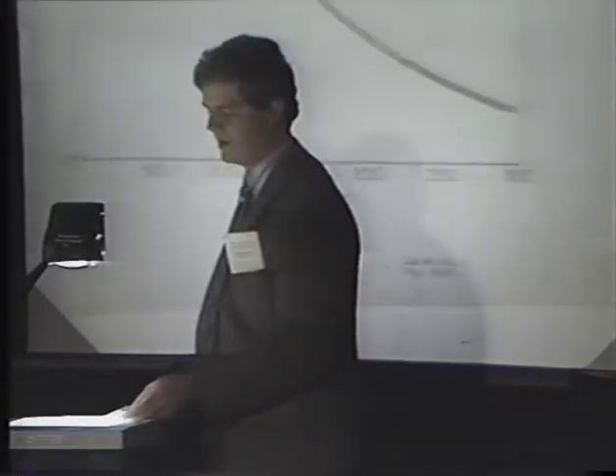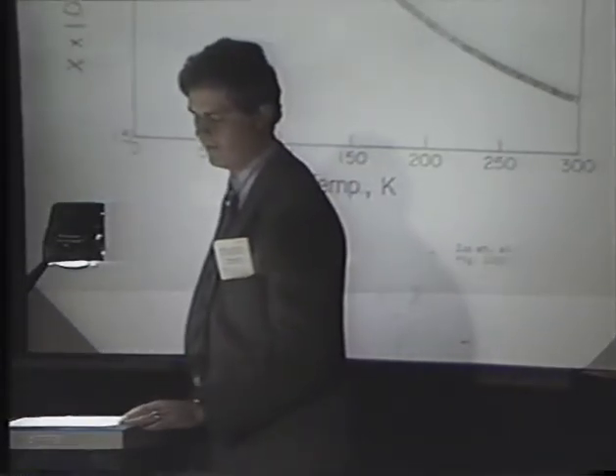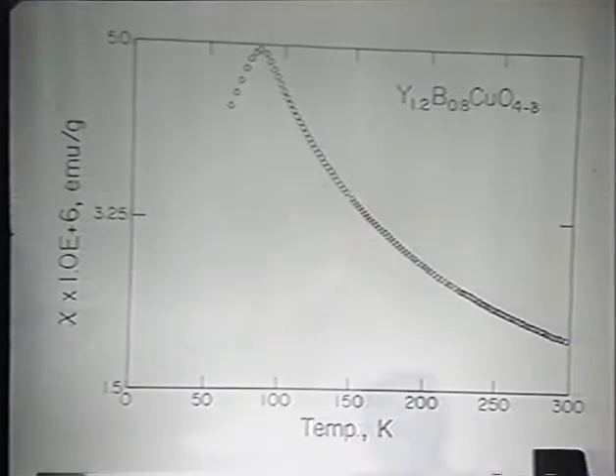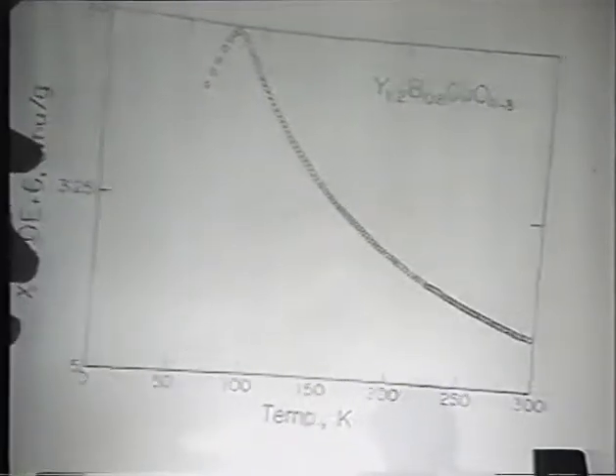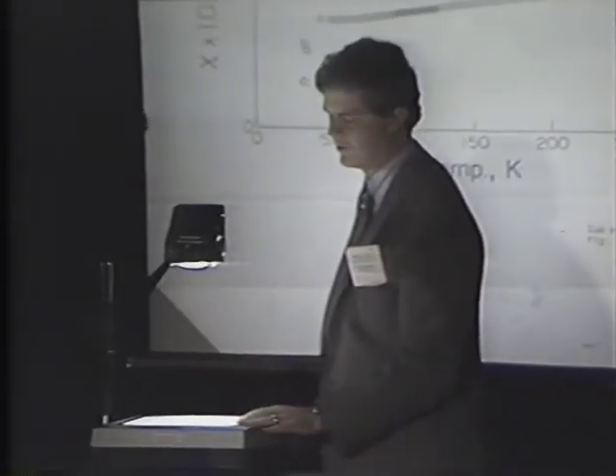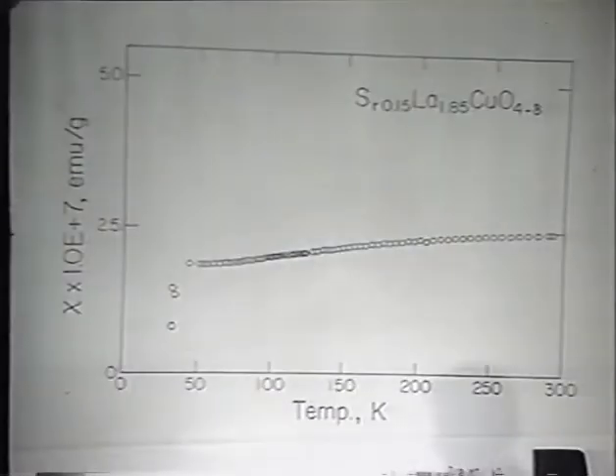If we measure the susceptibility with a Faraday balance for the yttrium samples, we see an extremely strong paramagnetic contribution showing up in the results. By contrast, there's no such paramagnetic contribution if we do the lanthanum-based susceptibility measurements.